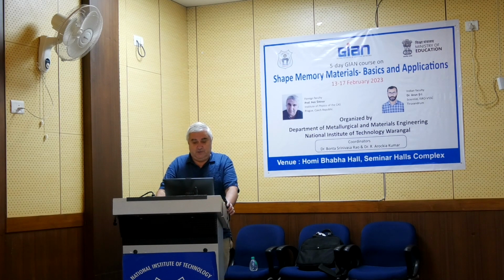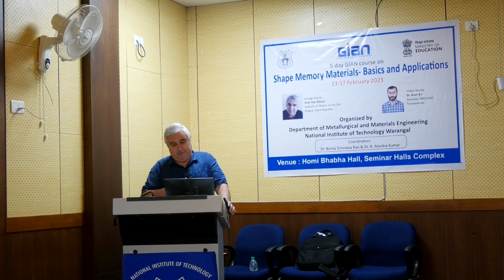Recently we are studying the plastic deformation of martensite. As I said, the plastic deformation of martensite occurs at high stresses beyond the yield stress, but unfortunately not only that, it also occurs if you use the wire in the range where only transformation should be. So if we do the superelastic cycle at 500 megapascal, the response is not completely stable.